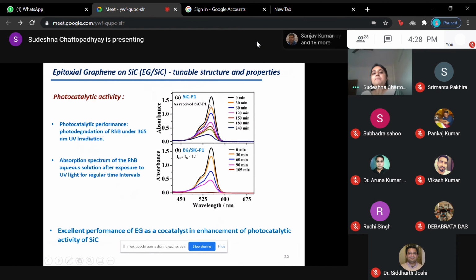Okay, so this dye has been used to probe the photocatalysis activity of the SiC, silicon carbide. Additive-free silicon carbide means there is no interface effect or graphitization. You can see that after 240 minutes, of course silicon carbide has photocatalytic activity as I have told earlier, that's why we have chosen it. But after 240 minutes even, it is still there. Methylene blue has not been destroyed, dissociated completely.